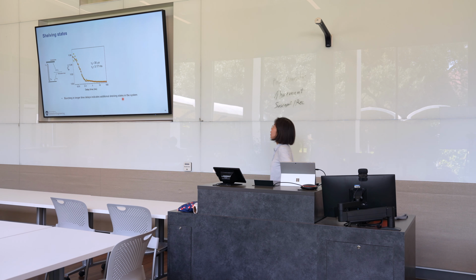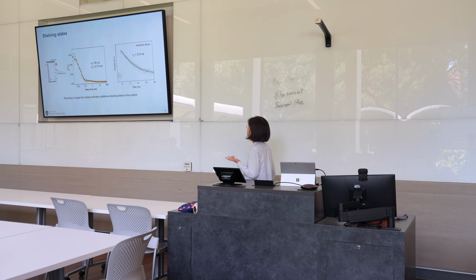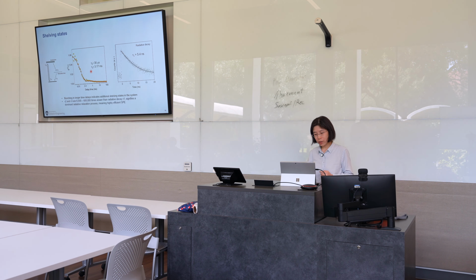In addition, we realize our emitters have shelving states. So if we measure this g2, the second order autocorrelation function, with a long delay time, we see a bunching feature. This bunching feature indicates there are some very slow decay processes, and we actually have two additional decay lifetimes, about 30 microseconds and 3 milliseconds. This slow decay indicates there are metastable states involved in the defect emission. If we compare these lifetimes to the radiative decay lifetime, which is about 5 nanoseconds, we realize tau2 and tau3, the slow decays, are about 6,000 to 600,000 times slower than the radiative decay. This signifies a dominant radiative relaxation process, meaning highly efficient single photon emitters.